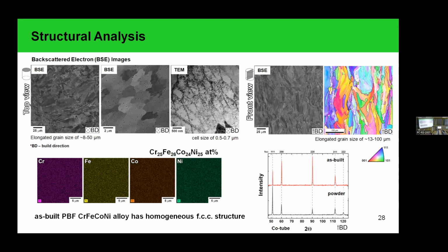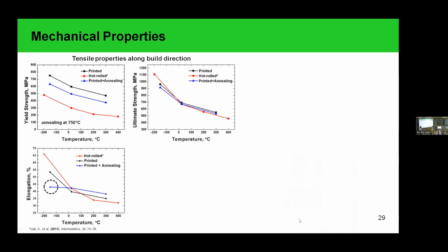And the analysis of the chemical composition demonstrated an approximately homogeneous element distribution. X-ray diffraction analysis demonstrates the presence of the face-centered cubic structure only. And also, which is typical for additive manufacturing materials, there is a strong texture along the building direction. On the next stage, we analyzed the mechanical characteristics of our materials in a wide temperature range in the as-built state and also in the annealed state, since annealing is a common post-treatment for additive manufacturing materials due to the strong residual stress in this material.